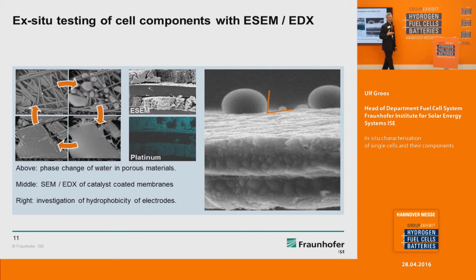And so you can apply freeze-thaw cycles to your components and look at the change of material properties, maybe the hydrophobicity. The ESEM is combined with an energy dispersive X-ray, so we can analyze the element distribution in the sample.